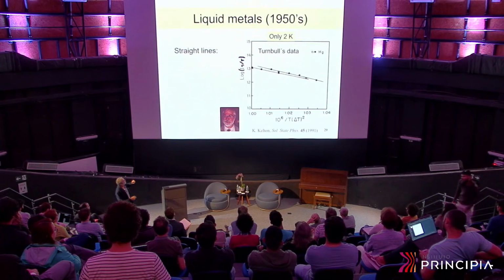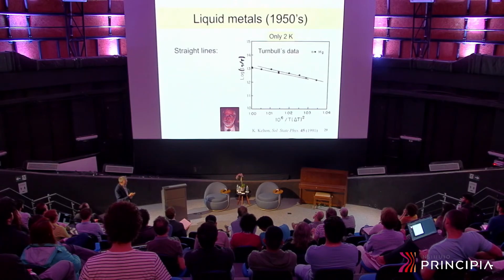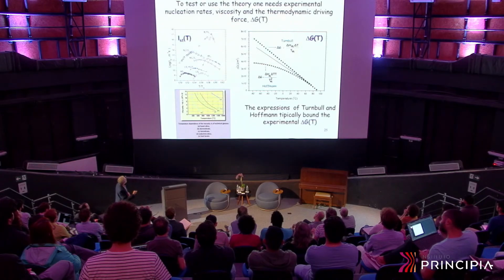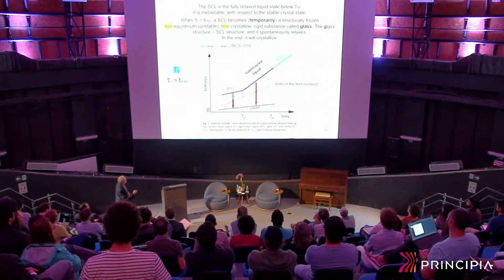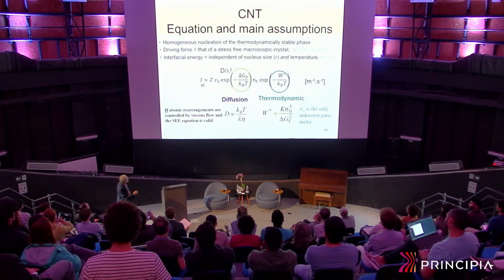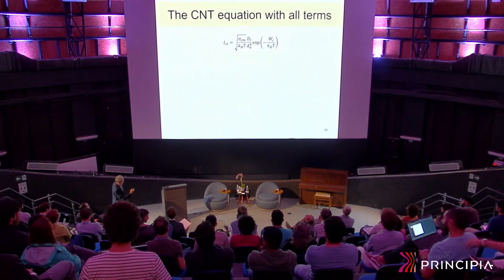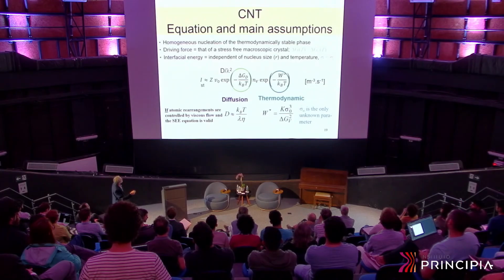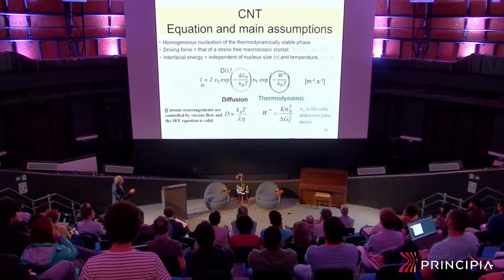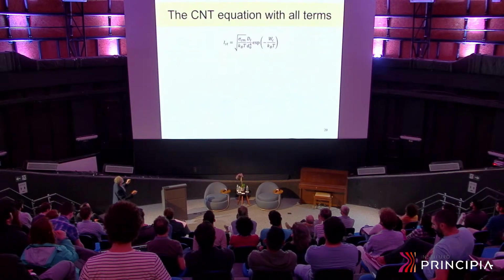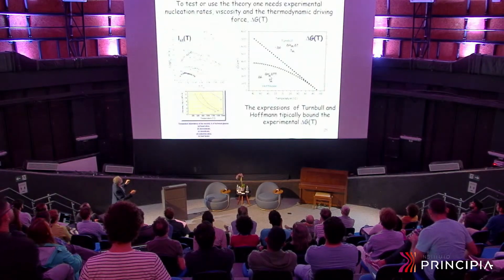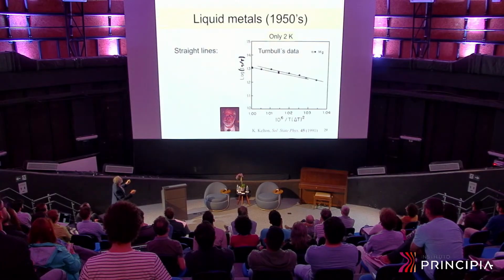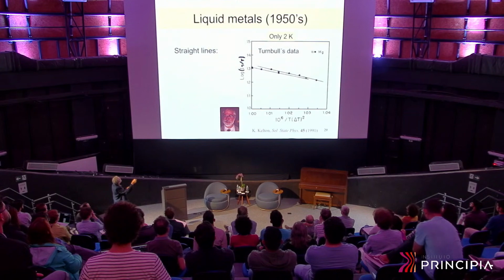Okay, good straight line. Let's then extrapolate here and compare the value of the pre-exponential factor with the theoretical value. We plugged in the viscosity for this part, 1 over delta G squared for this part, and want to compare with the theoretical value. This theoretical value can be calculated, so we compare the extrapolated value from the experiments with the theoretical value of the pre-exponential, using sigma as a fitting parameter. So we extrapolate here, get the pre-exponential and compare.